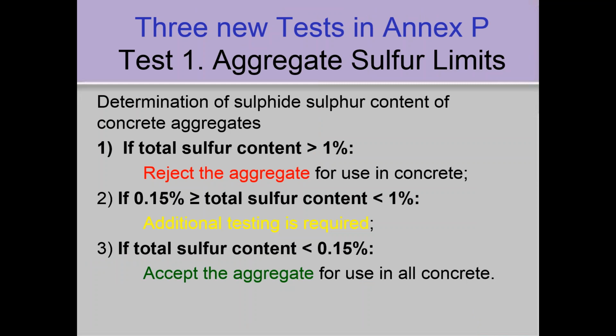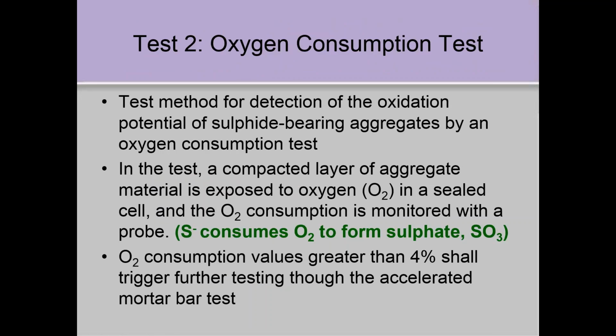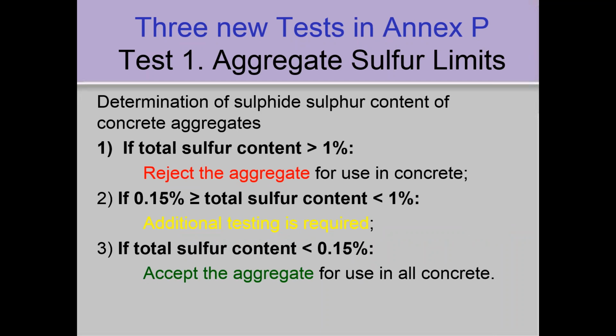So the test methods we've thrown in there is to look at sulfide sulfur content of aggregates, and if it's greater than 1% of the total sulfur, you're supposed to reject the aggregate. If it's greater than 0.15% but less than 1, you need to do some of these testing. And if it's less than 0.15%, you can accept the aggregate without any testing. So it's going to require aggregate producers to measure the sulfur content of their aggregates. That's going to be a new requirement. And so that's the first test, test the sulfur.